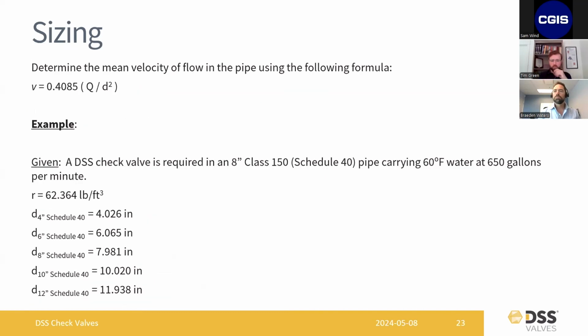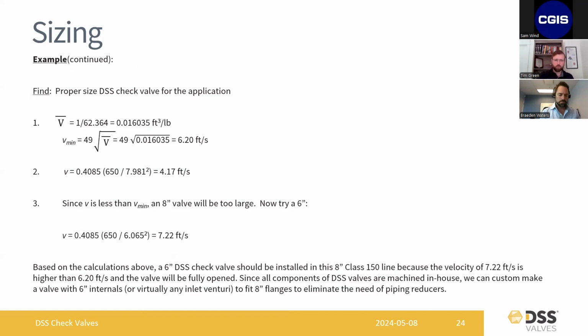The next piece of the puzzle is when you're sizing a check valve, you need to know what velocity the check valve is actually seeing. There's a standard formula for determining mean velocity of flow in the pipeline. I won't drag everyone through a math calculation here, but the gist is that you run a calculation. We know our valve takes 6.2 feet per second to remain fully open and stable. We look at the mean velocity in the pipeline, and in this case it's only around 4 feet per second.